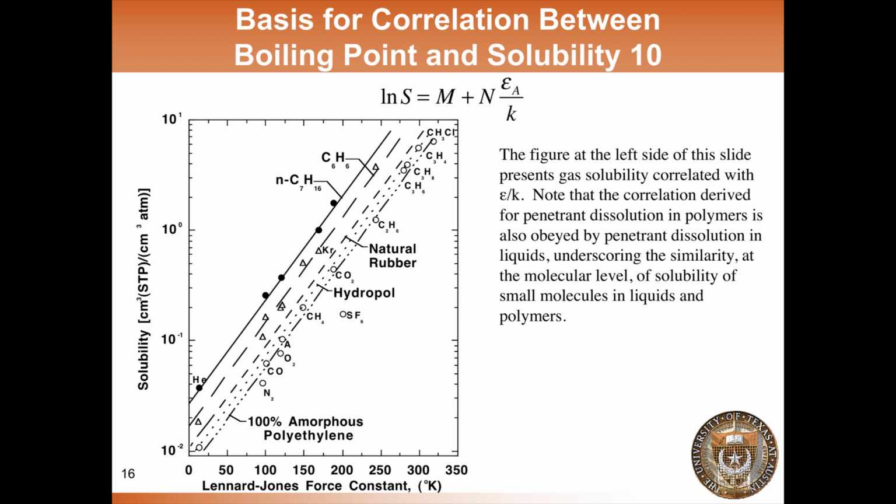Now, this is a really interesting plot, and it gets at the point that I was making just a moment ago, and that is that solubility often scales linearly or nearly linearly with Lennard-Jones force constant or with critical temperature.